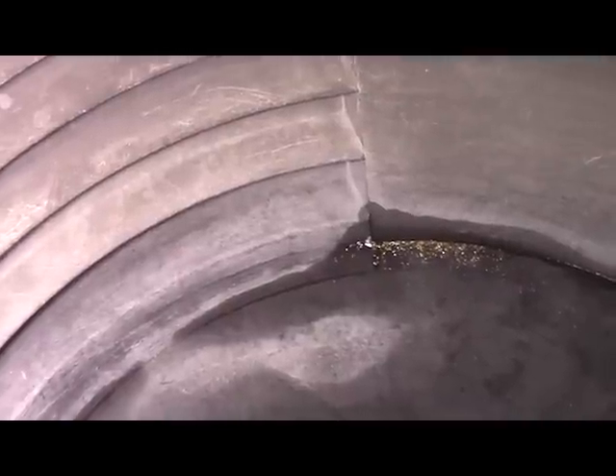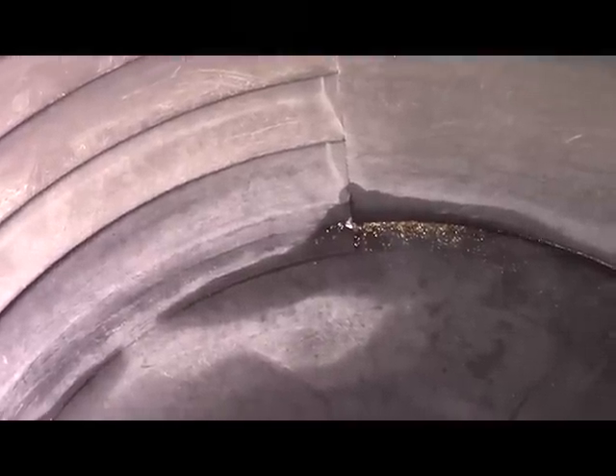These are the results from the finely pulverized output of the impact mill. You can see recovery has gone way up, at least the amount of gold, which would indicate that it's useful to crush it much finer because it is liberating it.